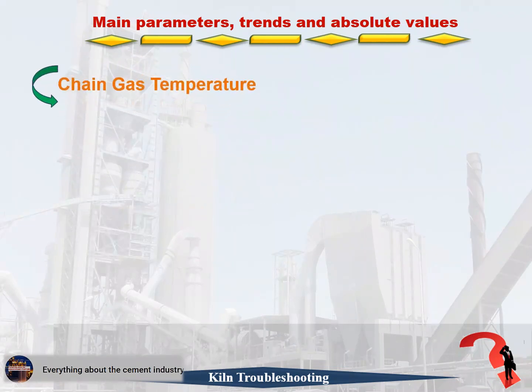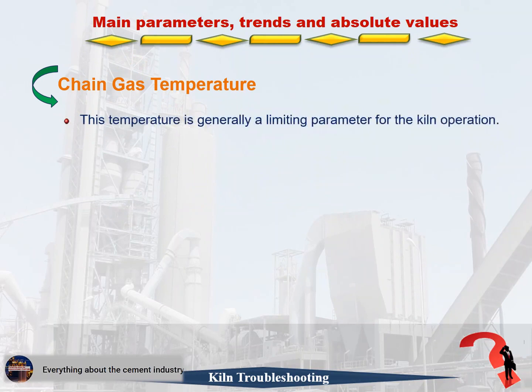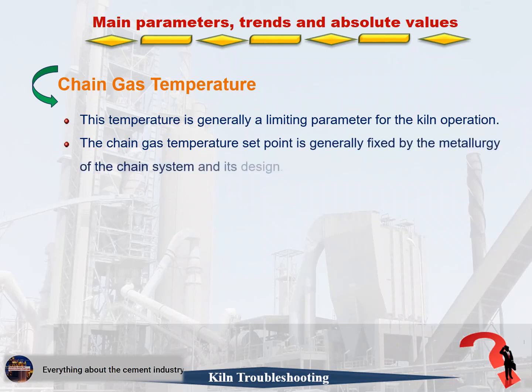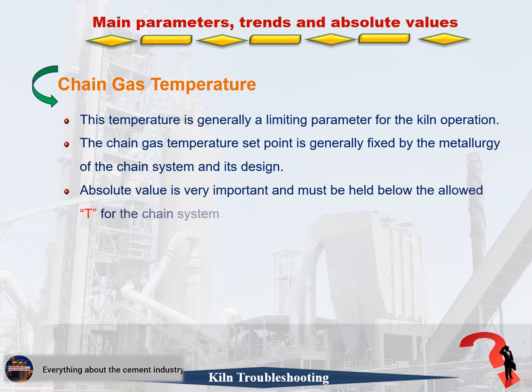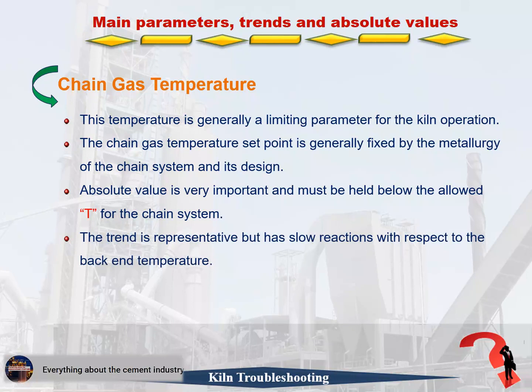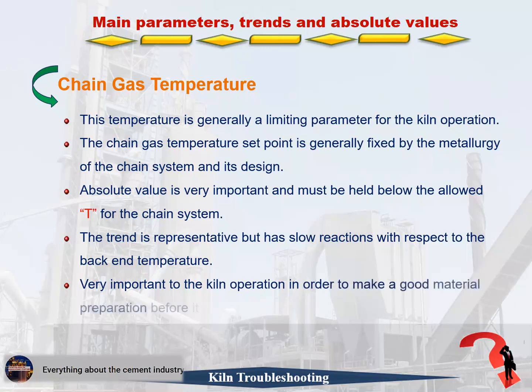Chain gas temperature. 1. This temperature is generally a limiting parameter for the kiln operation. 2. The chain gas temperature set point is generally fixed by the metallurgy of the chain system and its design. 3. Absolute value is very important and must be held below the allowed T for the chain system. 4. The trend is representative but has slow reactions with respect to the back-end temperature. 5. Very important to the kiln operation in order to make a good material preparation before it reached the burning zone.